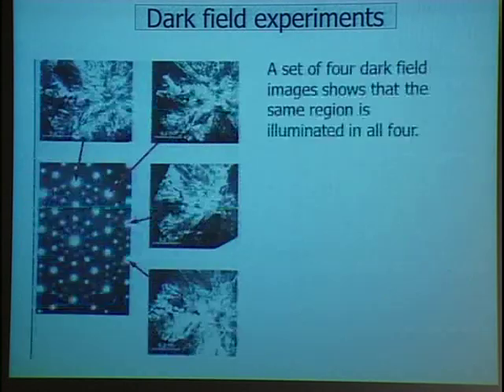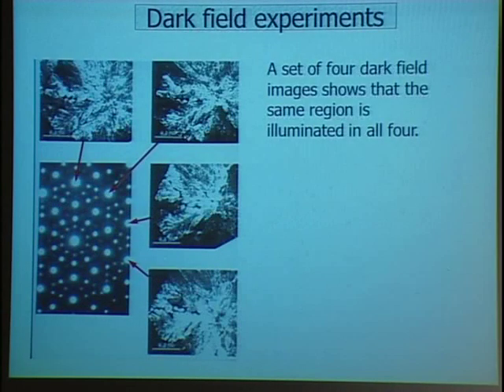So then I said, okay, these are obviously twins. Let's find the twins. In order to find the twins, you can perform several experiments in the microscope. One of them is called a series of dark field images, as it is seen here. A dark field image is something like that. You see, when you take a bright field image, you use the central spot, you block all the other beams, and you take a picture using this beam. This is called a bright field image.